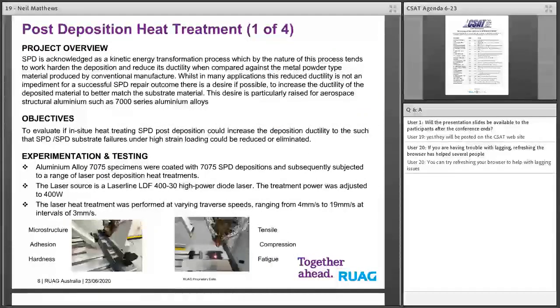We're just going to go through a couple of applications that we've been playing with. One of the requests was to look at whether we could post-heat treat SPD depositions, particularly aluminium alloy depositions, almost as an in situ process. Obviously, we're aware that the SPD deposition doesn't have the ductility of the substrate. So the concept there was to basically look at the post-heat treat. We have laser capability, so we looked at the potential of heat treating depositions with laser, and there are some pictures of what we were doing. And we were looking at a number of elements: microstructure, the effect on adhesion and hardness, and the mechanical property effect. Next slide, please.